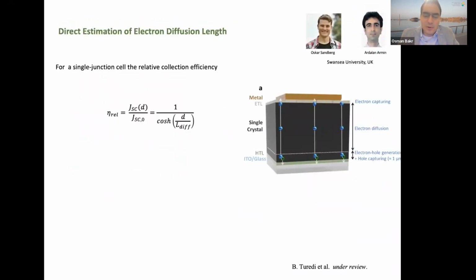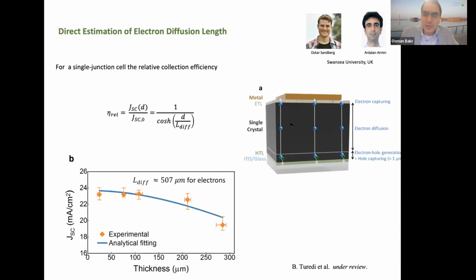So with our colleagues from Swansea, we started modeling the diffusion length, how the electrons diffuse based on the thickness of these crystals. And we were able, for the first time, to directly measure the diffusion of charge carriers in the solar cells, because we were able to control the thickness of the crystal. By fitting the short circuit current at different thicknesses, the current efficiency at different thicknesses, we were able to obtain a very self-consistent estimate of the diffusion length. And we found that this diffusion length was 500 microns, at least for the electrons. So this is very surprising.